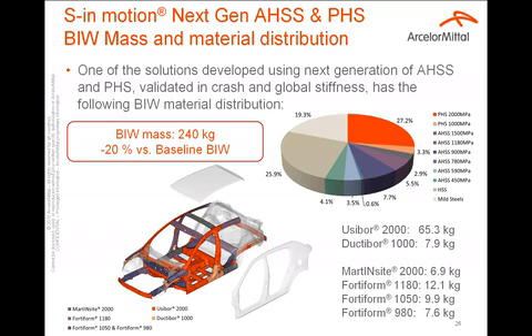One of the solutions of this project, validated in crash and global stiffness, achieved a very low body-in-white mass at 240 kilograms, meaning minus 20% weight saving, compared to a baseline around 300 kilograms, which is representative of the C-segment market. This solution has the following body-in-white material distribution, with more than 30% PHS, 27% of which is potentially manufacturable with Usibor 2000, all on the red part of the body-in-white structure.